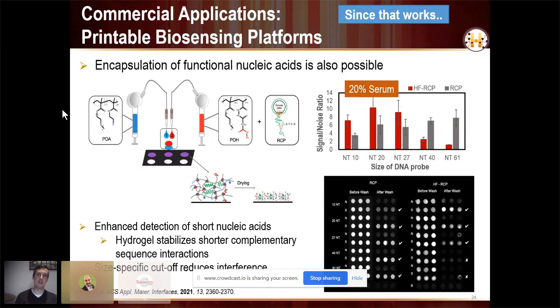On the other hand, if we're trying to detect very short base pairs, what we get is about a 2-fold increase in signal to noise. And what we think the reason is, this can easily diffuse into the gel, so we can still interact with this rolling circle amplification complementary DNA sequence inside the gel.